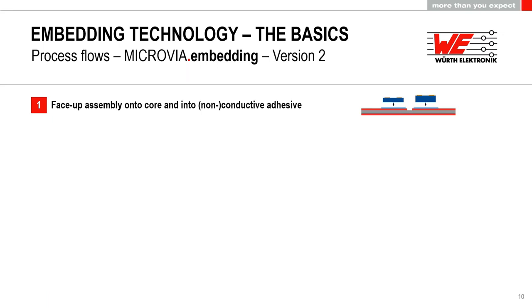There is a version two for this technology. In that case, we use a face-up assembly onto a pre-structured core, and we use either a non-conductive adhesive or a conductive adhesive, or, what I didn't write down here, we can do a soldering or a sintering of the component. So if we need a backside connection to the component, this would be possible in that case. Version one could offer a backside connection as well, but here we could only use a microvia process as well, and that means that the backside of the component in version one would need a compatible surface like copper, for example, to make these microvias from the backside.